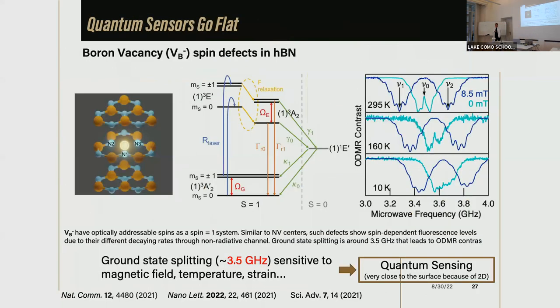So since I mentioned 2D materials, let me show this recent result, which is submitted. That's done with hBN, one of the very popular 2D materials. And this particular one, which has boron vacancy, is really good because this spin degree, which is related to the ground state, we split in 3.5 gigahertz, which means that you have a spin where you could record the information, it could be your qubit, and it's optically addressable because of different radiation rate for different spin state.